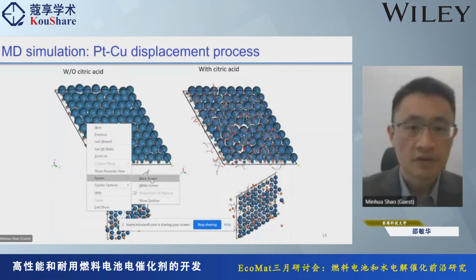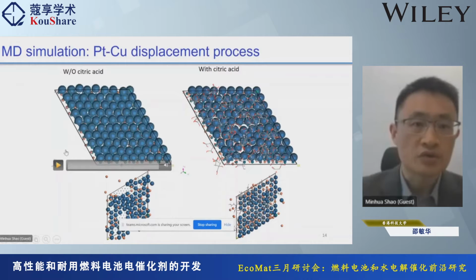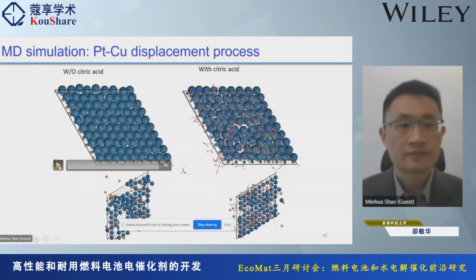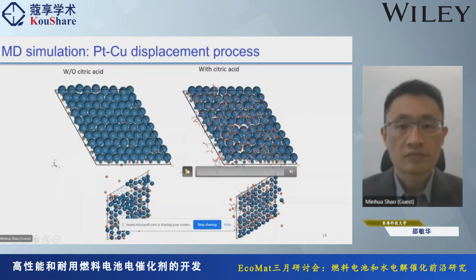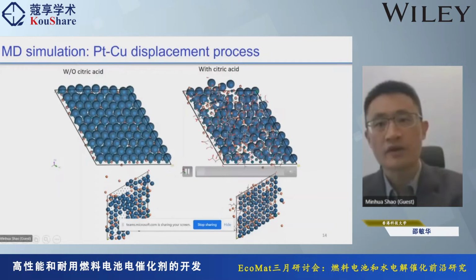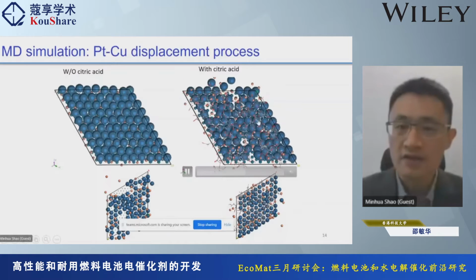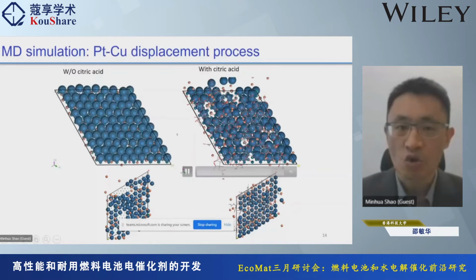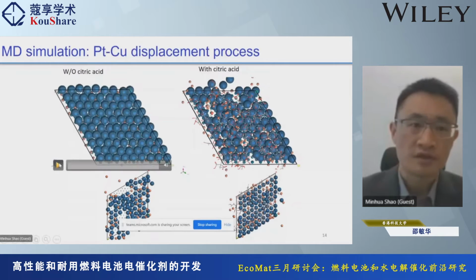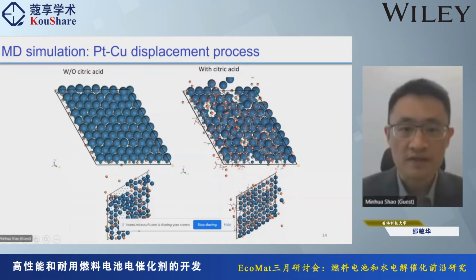So this one is without citric acid, and you can see how this platinum layer deposited on this copper surface without citric acid. It will probably take time. Right. So the second one is with citric acid, you can see that citric acid actually prevents the formation of large holes. Okay, this is with citric acid. Sorry, this is probably taking too long, but you can see the final result.